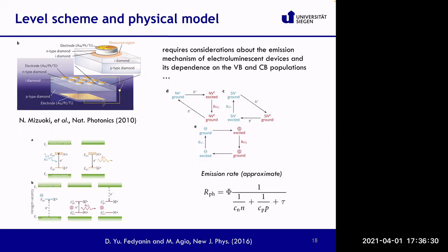Now what we want to do is to use electrons and holes that you deliver through the conduction and the valence band, respectively. And so you have to be more careful. So what happens? You have the ground state of your nitrogen vacancy, and this ground state picks up a hole from the valence band, and then it becomes essentially a neutral state, because the charge state changes. Then what happens? This hole has to essentially go to the excited state in order to emit a photon.